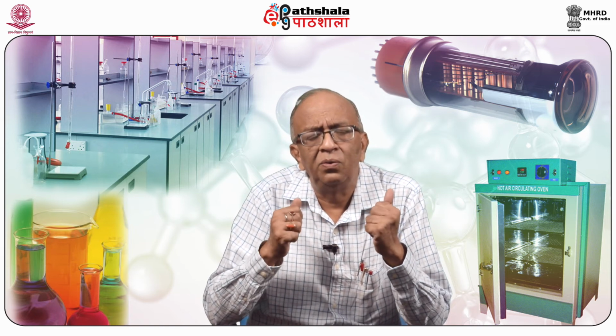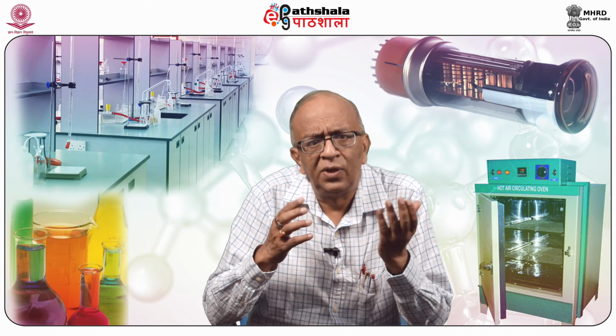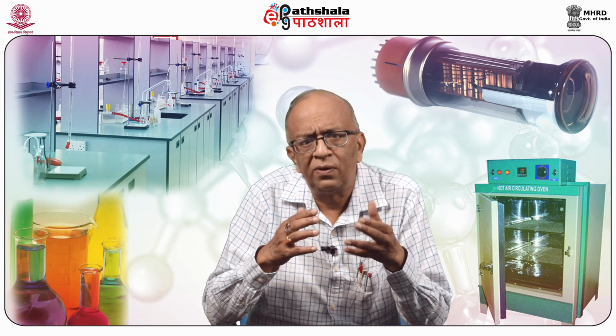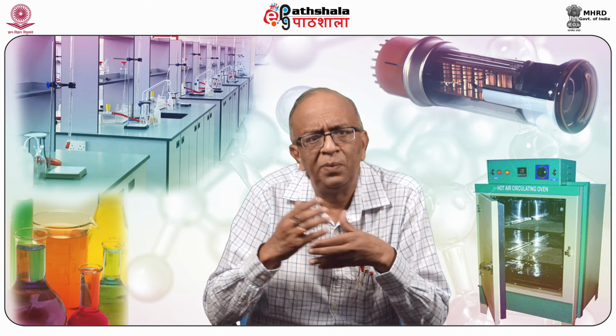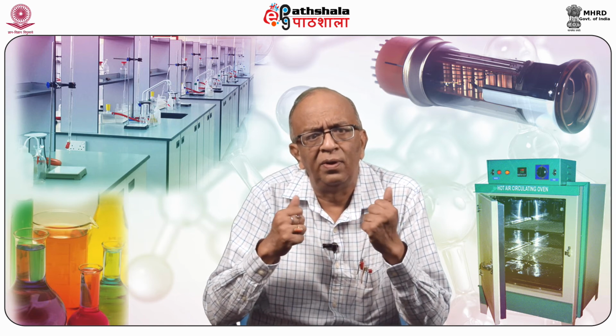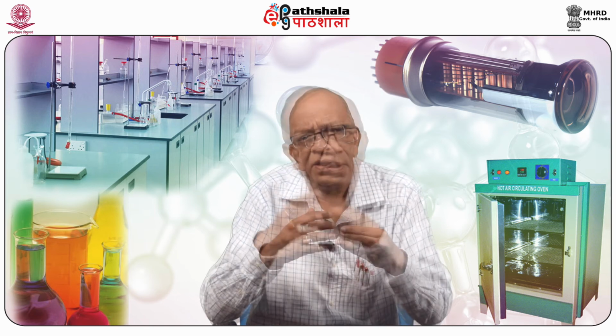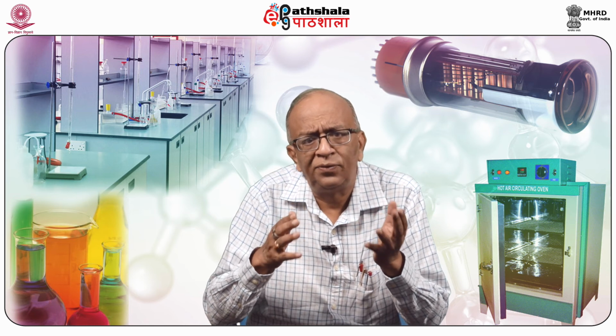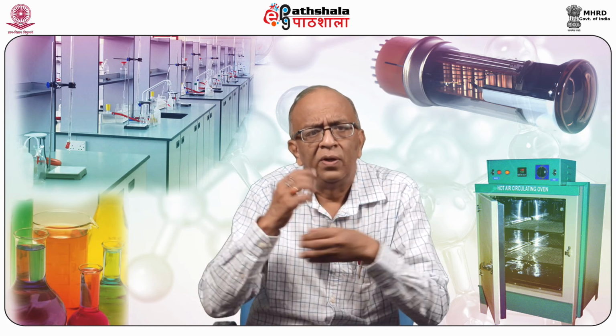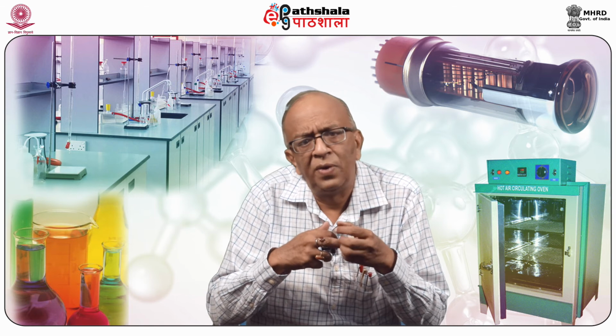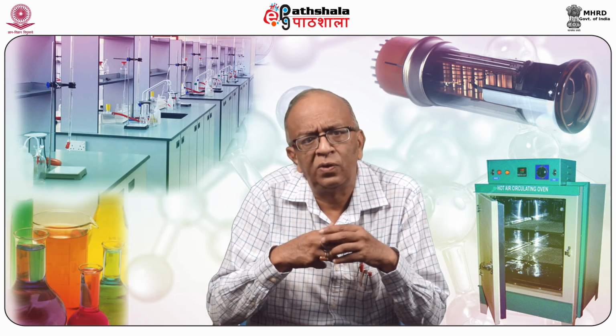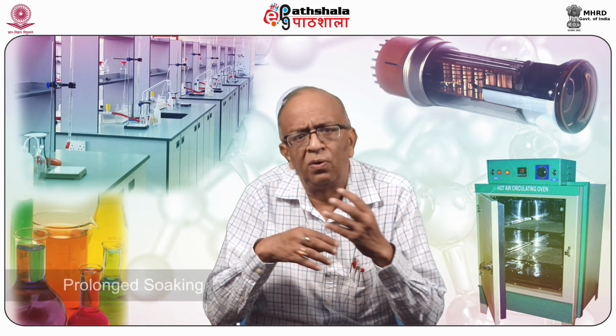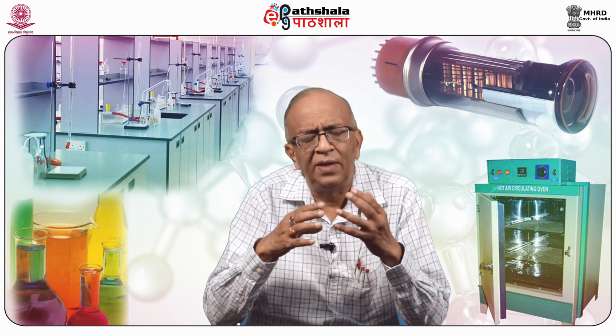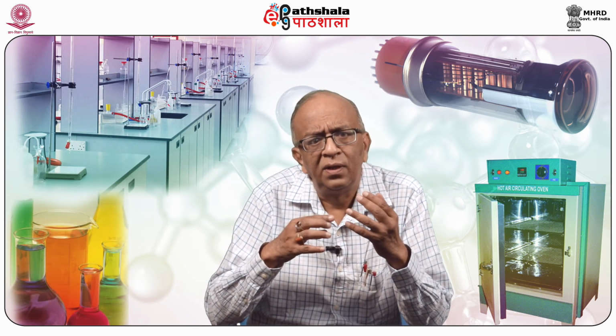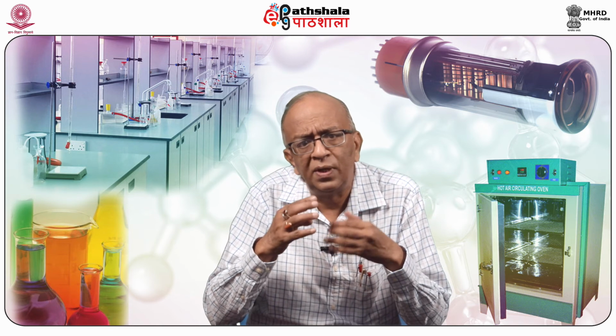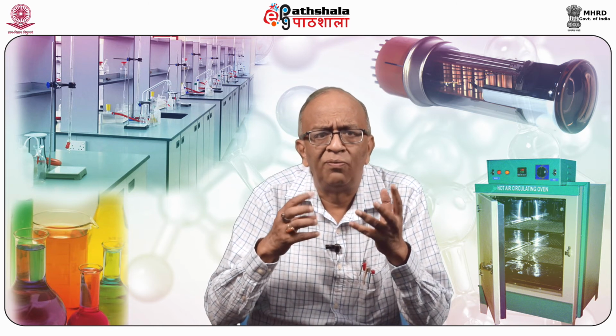It is important to know the weight of the resin used. It must be dried or brought to a known moisture content in a hygrostat, that is, in a vessel with controlled constant humidity. In any event, before packing, it must be equilibrated with water by prolonged soaking. After the resin has settled, the fines which float in the water are poured off.